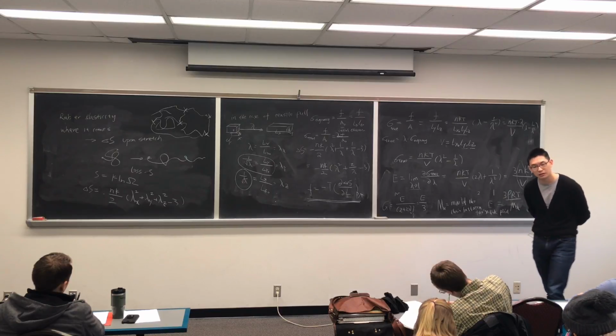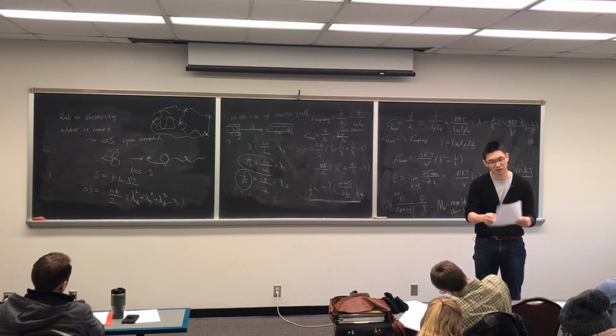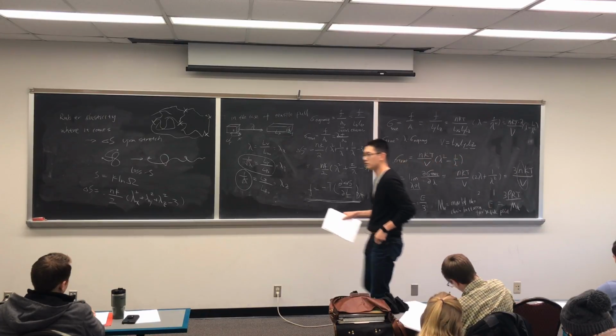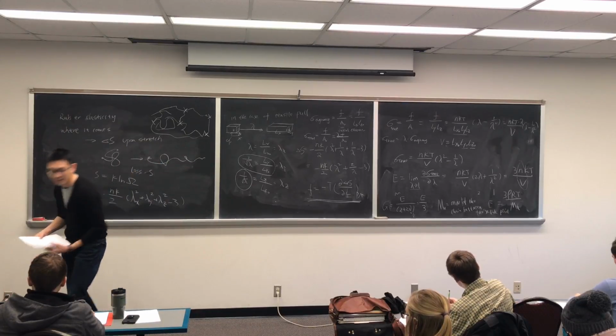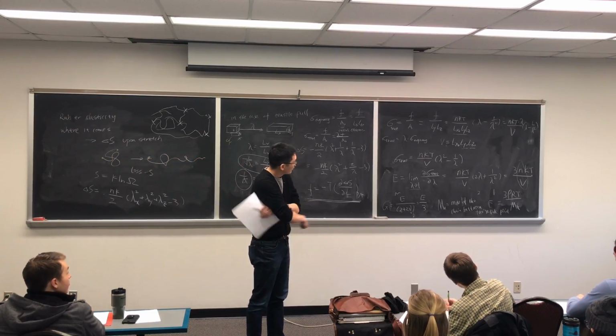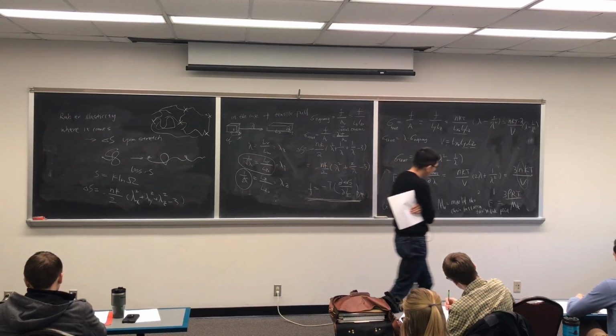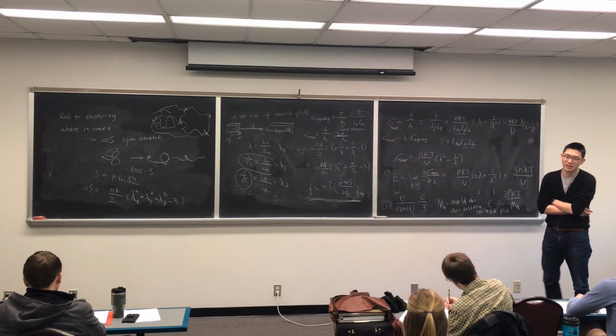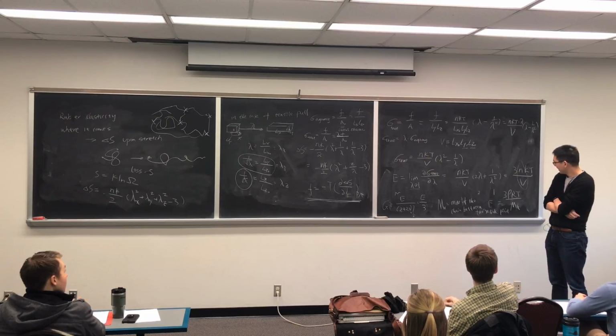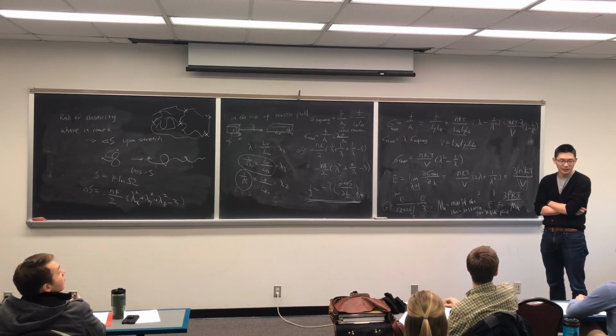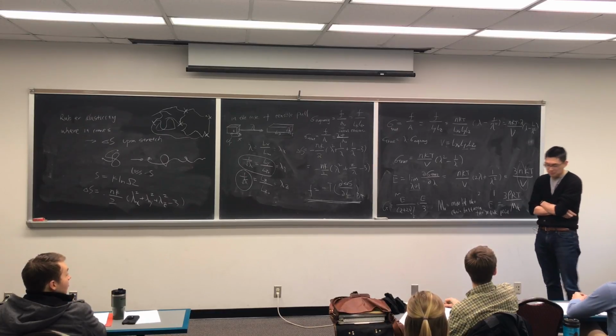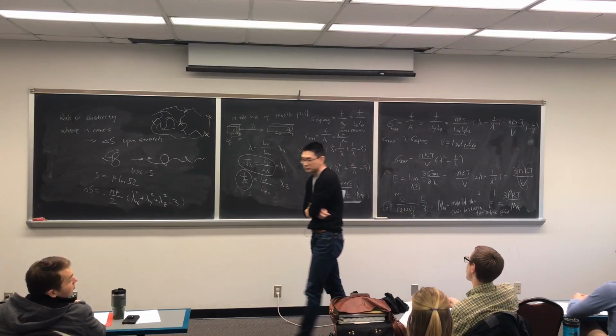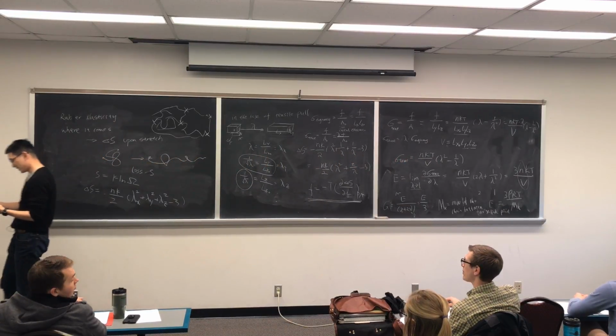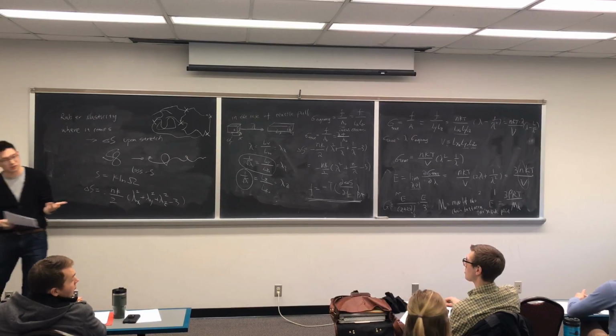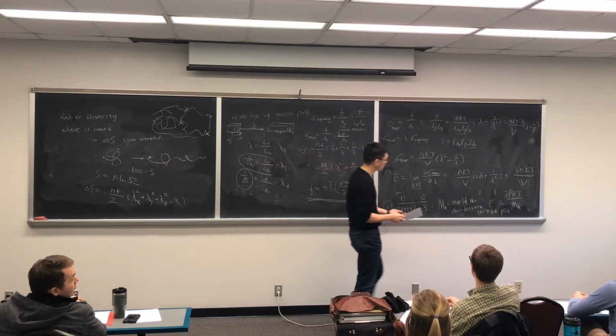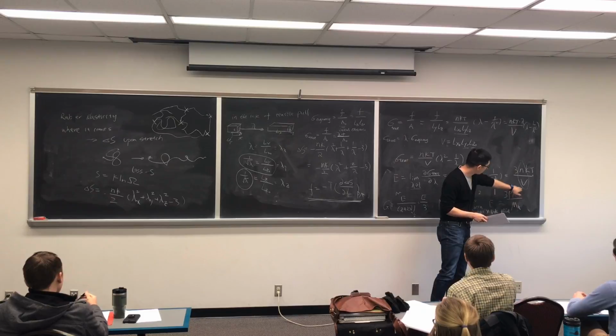For incompressible material or rubber material, where you pull it in one direction, in the perpendicular direction your deformation is half of your tensile direction. Okay, so it was quite a success for the community to see this type of understanding in the rubber material. It explains why a rubber band would contract. It explains how the rubber material depends on how you crosslink it. And so the community was very happy to see this, right? Because if you know a certain modulus you want to get, you can roughly know how much you need to crosslink, because elastic modulus is directly proportional to crosslink density.